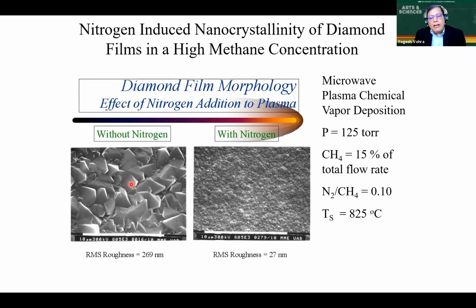But as soon as you put a little bit of nitrogen in the plasma, the details are given here, if nitrogen to methane is about 10% of methane, you see that the film becomes very fine grained and becomes very smooth. And one of the drawbacks of application of diamond film technology has been the surface roughness. These films are too rough for most applications, and they scratch the opposite articulating surface with the growth chemistry morphology like this. So this was a very exciting development.